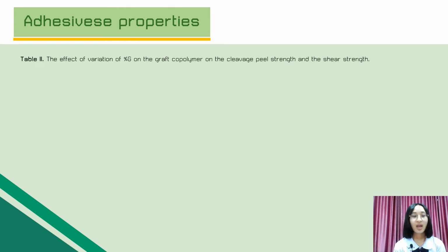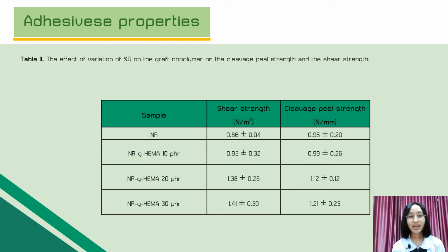Adhesive properties. It was found that the cleavage peel strength and the lap shear strength increase as the HEMA concentration increases, and the graft copolymer has a higher strength compared to the NR.